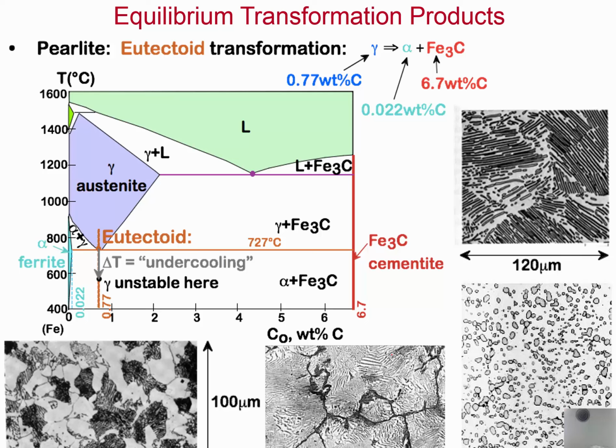Another good question is these two. Can you estimate carbon contents on these? Again, this is about 50% ferrite, 50% pearlite. Put it about there, about 0.4% carbon. This one here, this is clearly hypereutectoid. You're seeing carbide formation on the prior austenite boundaries.